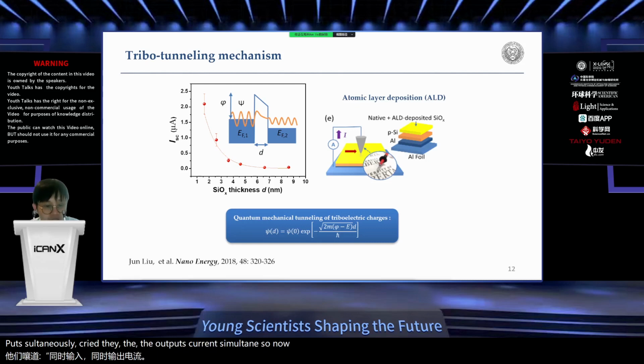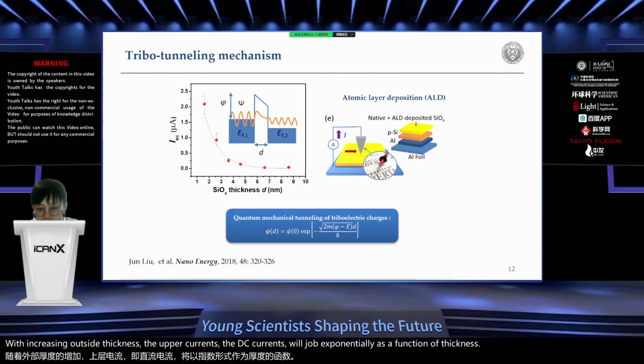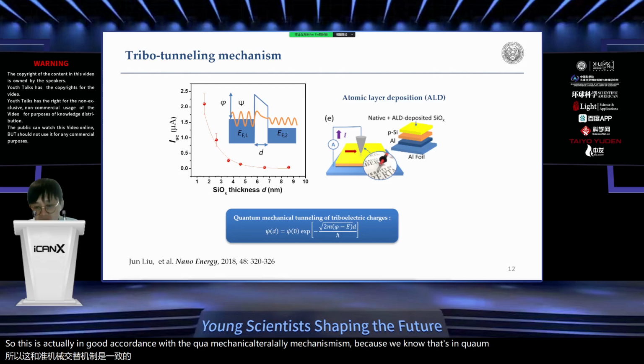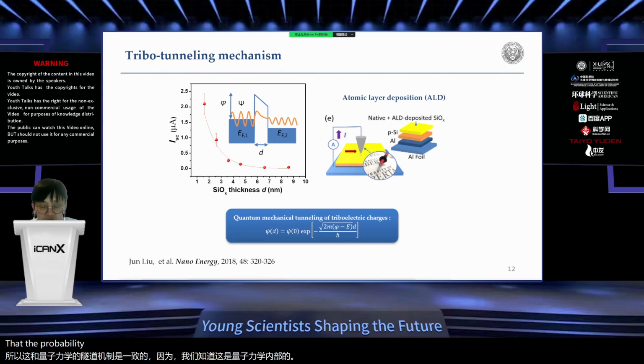So now we can see that with increasing oxide thickness, the output DC currents will drop exponentially as a function of thickness. This is actually in good accordance with the quantum mechanical tunneling mechanism, because we know that in quantum mechanical tunneling, the probability of charges getting through an energy barrier follows this exponential law.